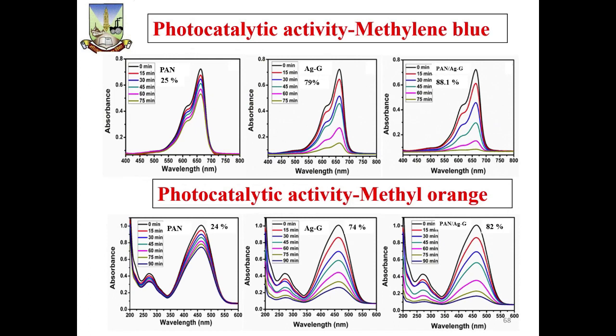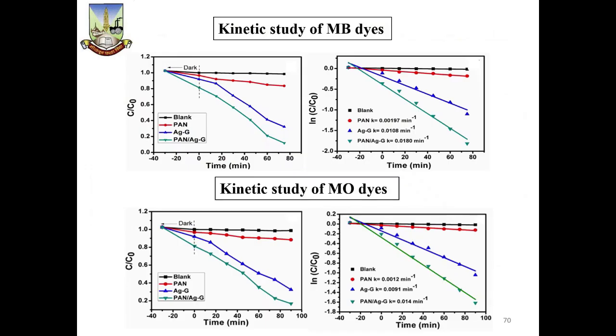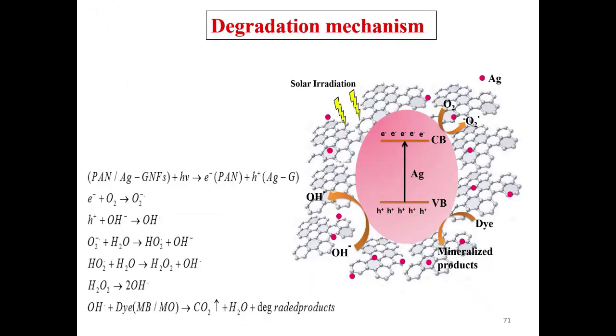In the presence of the catalyst, from 0 to 75 minutes, and here from 0 to 90 minutes, very high degradation is taking place for both. We have done the kinetic study for methylene blue as well as methyl orange. It is found to be a pseudo first order reaction. This is the degradation mechanism, a very elaborate, very descriptive mechanism.